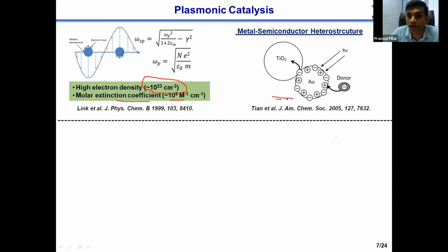So they were trying to make heterostructures with semiconductor nanoparticles like titanium dioxide, and they will excite the nanoparticle. You will get the hot electrons. These hot electrons will get transferred to the titanium dioxide, and it will improve the catalytic efficiency of titanium nanoparticles. So basically, in these kind of studies, gold nanoparticles were used as an antenna.